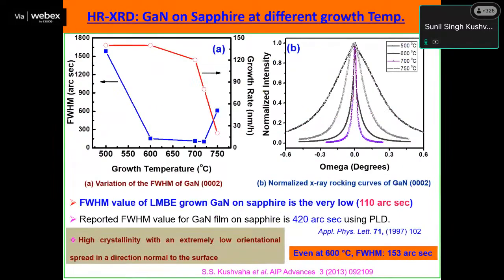This is one of the examples we have done. This is our 2 theta omega scan, and this is the XRC rocking curve. It looks like this, and we have the different temperatures. From here, we can see that when the temperature is 700, we see a very low FWHM, which shows the very high quality of the film formation.